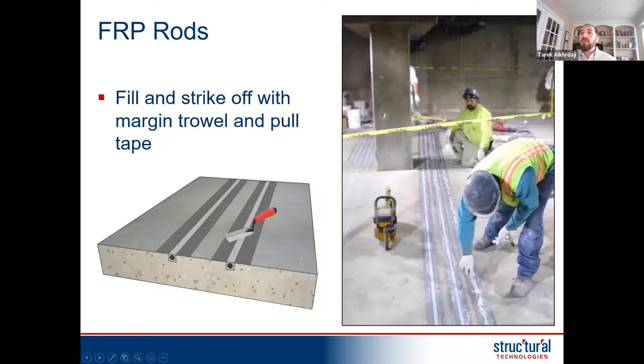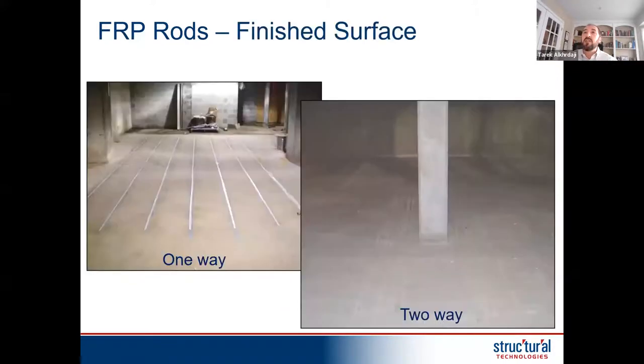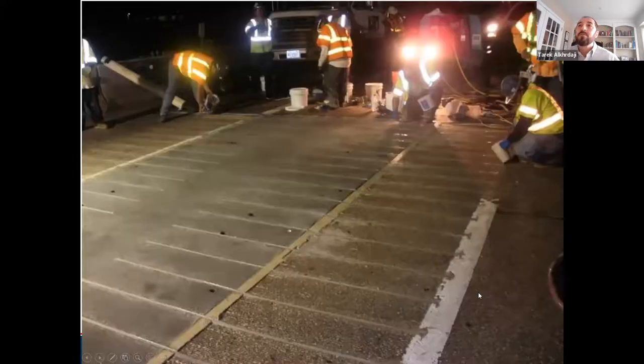You can see in here one technique, this is what the workers have done. They put some tape on both sides, like when you paint, exactly, put the bar in with epoxy. And once they're done, they pull the tapes off to make sure it has nice and clean edges. And this is the bar after it's done. You can see it's still a little bit shiny in the photo on the left, mainly because it still did not cure. And to the right, it's hard to see, it's fully cured. You can see bars actually installed in two directions. I know it's a little bit harder to see in the photo, but they're actually showing bars on all four sides of the columns in two directions.